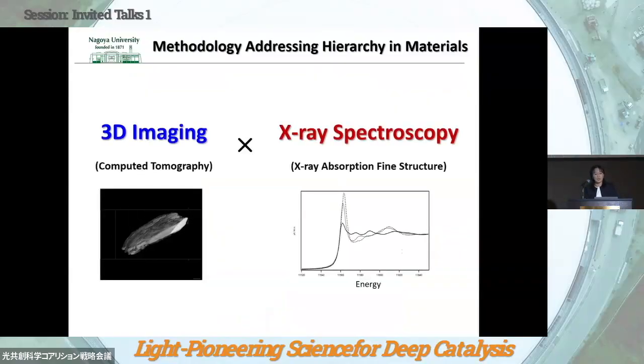And advances in X-ray imaging over the past decade have significantly enhanced our ability to visualize the structure of materials. However, structural information alone is insufficient to understand the chemistry involving molecular transformations. Chemical information, such as valence state, coordination structures, and chemical interaction, is indispensable for chemistry research. X-ray absorption fine structure is a powerful technique to provide such chemical information even for amorphous materials. So extending XAFS spectroscopy to three-dimensional imaging requires significantly higher sensitivity than conventional structural X-ray imaging.